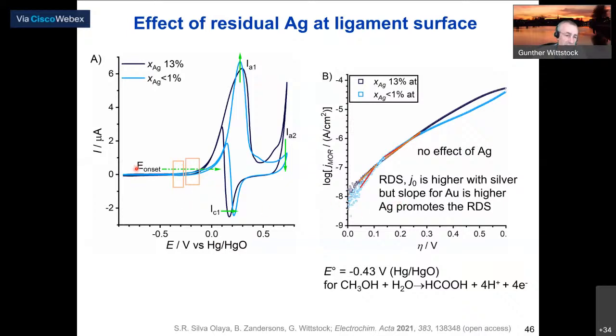If we translate that for these two regions to Tafel slopes, we get these two regions, and then we see, okay, with silver, the initial current is higher, but the slope, I mean, the increase of current with potential is for the clean gold surface larger. And in this region, there's basically not too much of a difference. So we conclude it's essentially still the same mechanism. Just the initial step, the rate determining step, is accelerated by the presence of silver at that potential region.